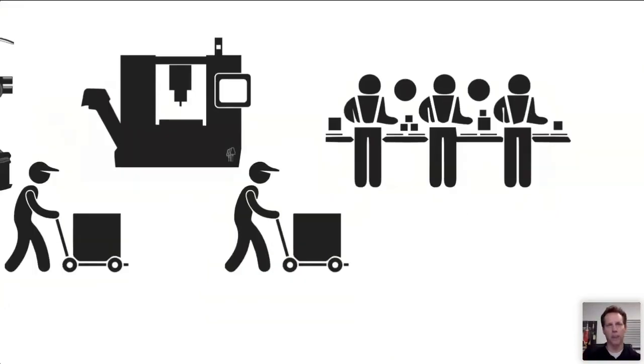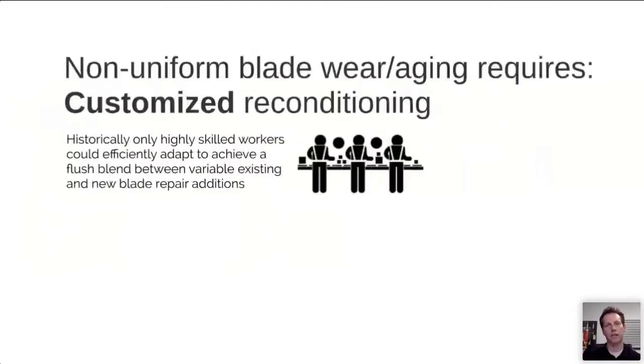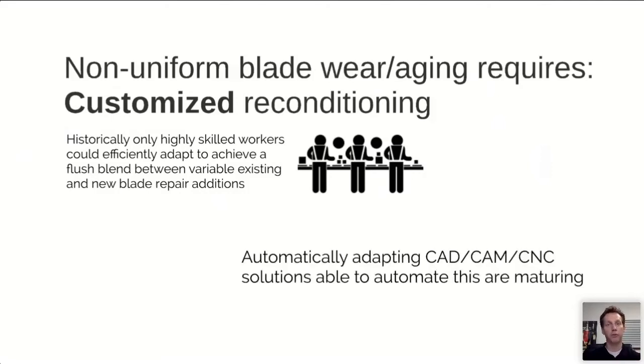To add to the complication, when we talk about repairing parts that have already been in service, they do not match one another, right? There's an original CAD drawing for sure. Often these parts are cast. Once they're cast, they don't match each other perfectly, but certainly after they've been in the field for thousands of hours in use, they're different. And as a result, this ends up becoming a customized process. Every single blade that comes in needs individualized attention. And for the longest time, operators, very skilled people, were the most practical way to do that. However, as CAD/CAM gets better and our ability to inspect and create a digital twin improves, now we're seeing CAD/CAM solutions that can adapt to each new blade presented to it and be scanned on the fly and then move forward. So it's a really exciting time.